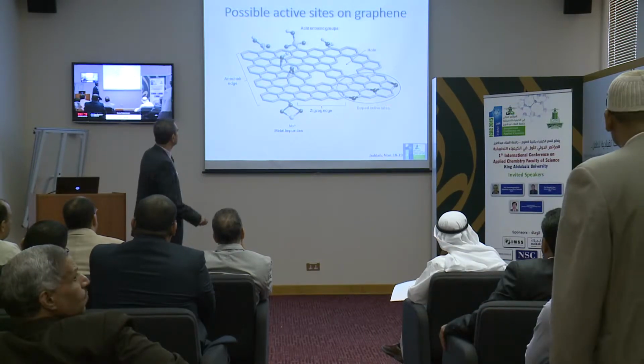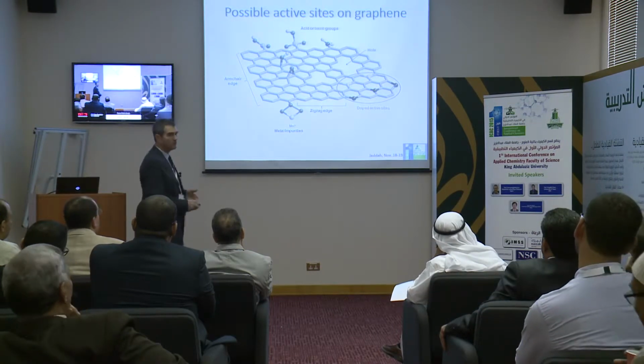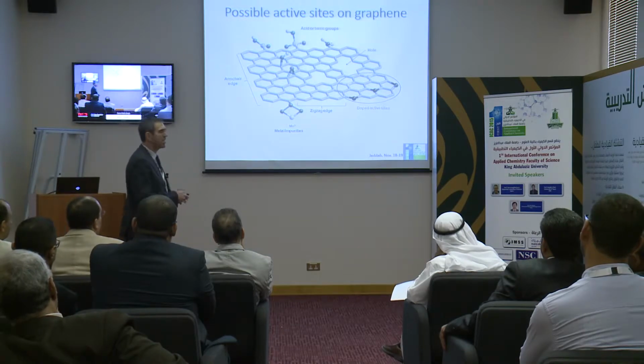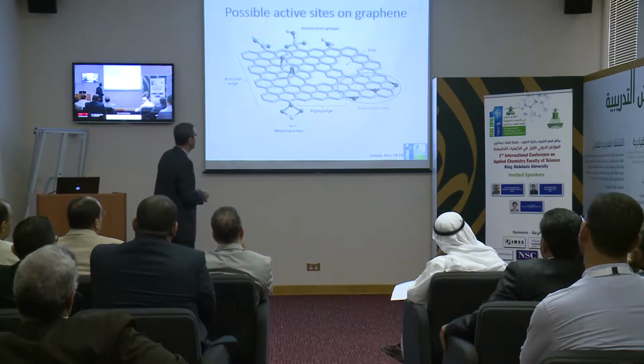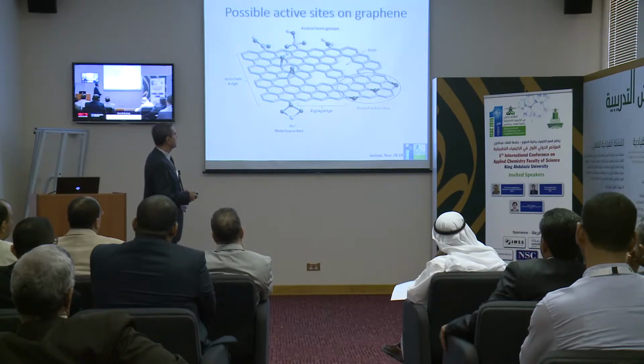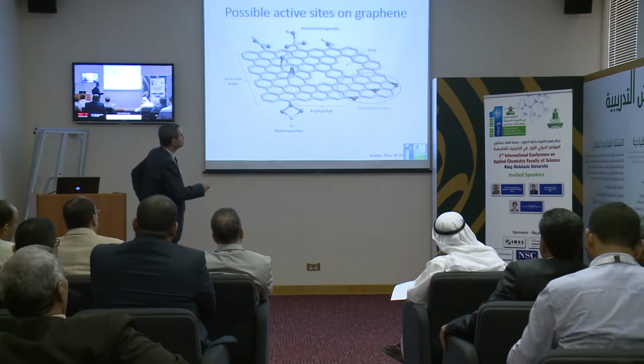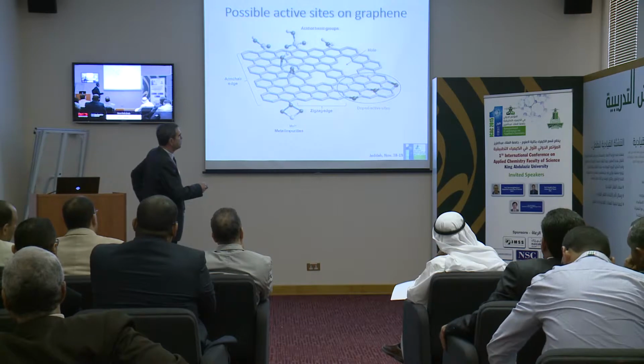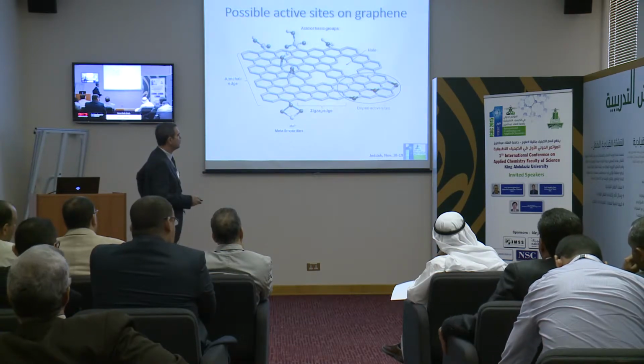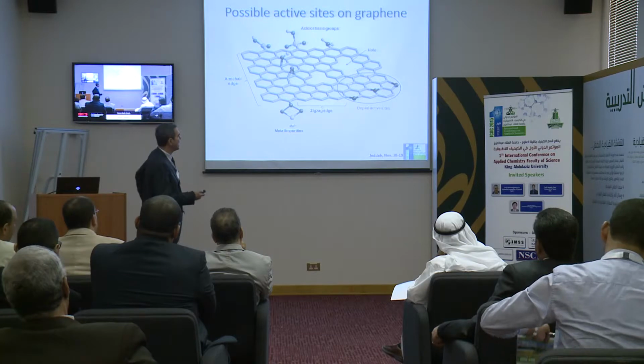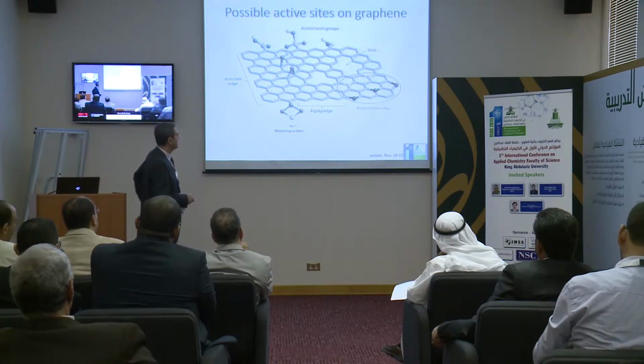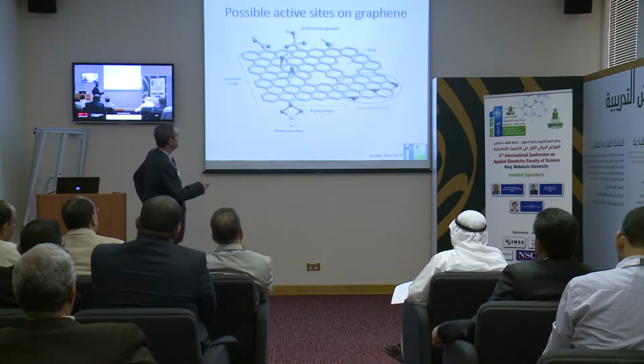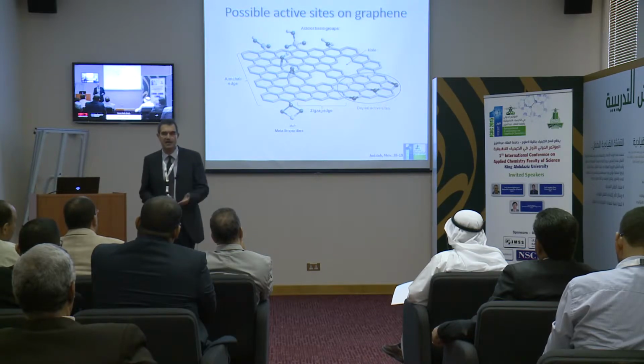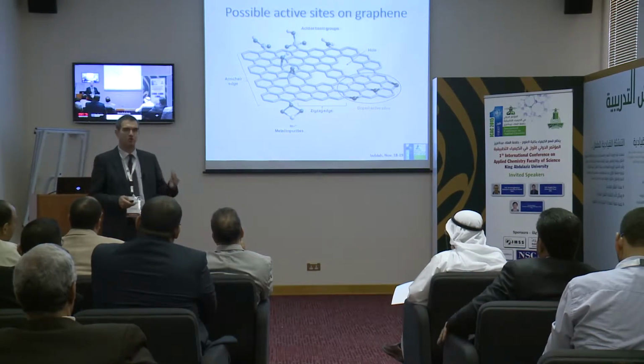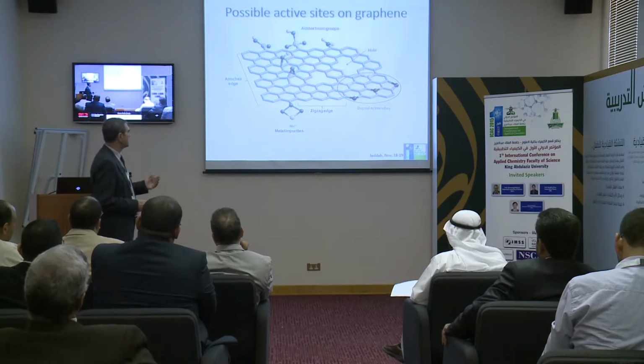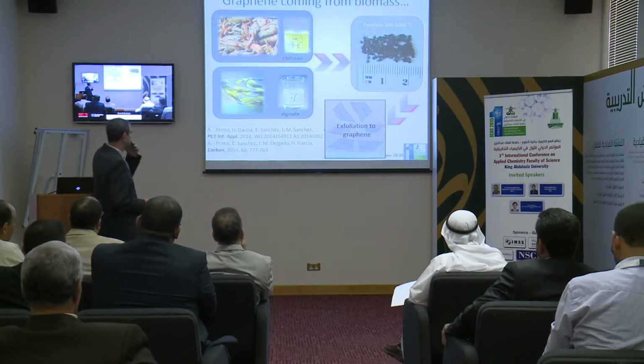But also, other active sites are oxygenated functions. For instance, I will comment that quinones and hydroquinones are really very good redox pairs in graphene. And also we can introduce some other heteroatoms, for instance boron or nitrogen, and in that way we can introduce acidity on graphene, and also we can introduce basicity on graphene. So basically the point is that it is possible to engineer a graphene that contains the defects that can act as a catalyst in organic reactions.